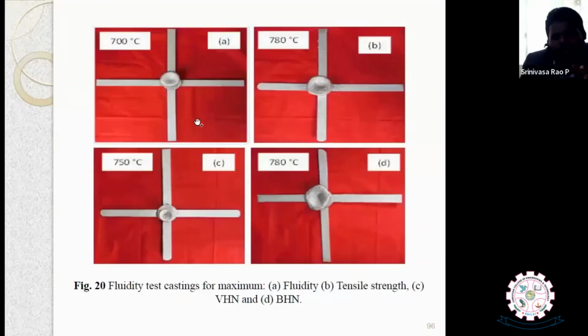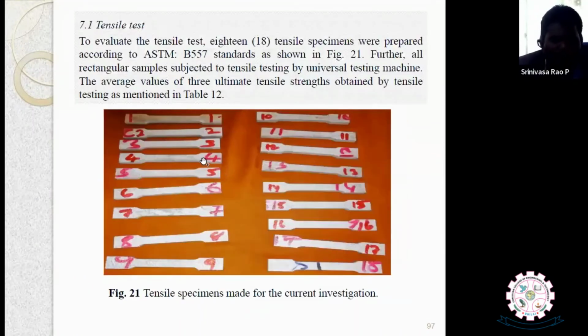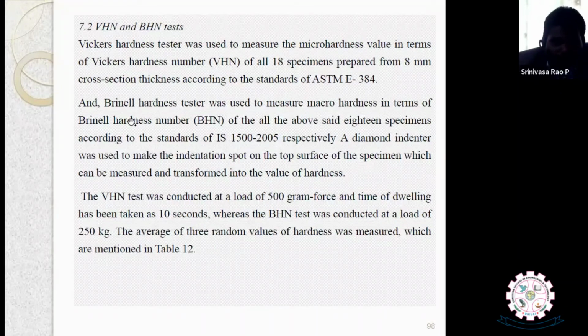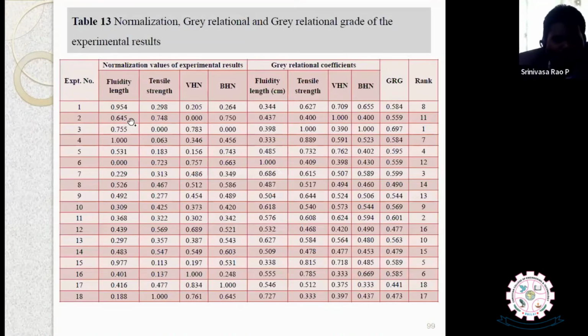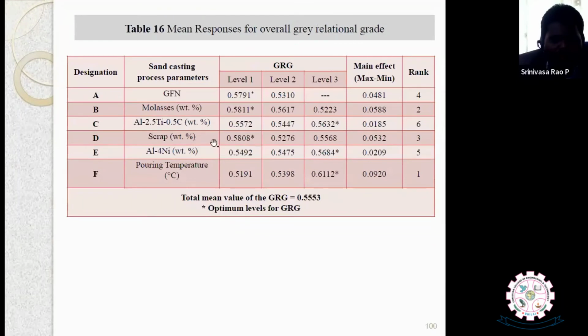Then we have taken the sample from the cross section and made tensile test specimens to carry out the mechanical properties, tensile strength, etc. And then we have also measured mechanical properties like Vickers hardness and Brinell hardness. So using the Gray relation analysis technique, we did the normalization and found the Gray relation coefficients, and these are the Gray relation grades. In this one we see the third one shows the grade 1. That means this is the best. If you do the mean response analysis overall, you can see the star mark.